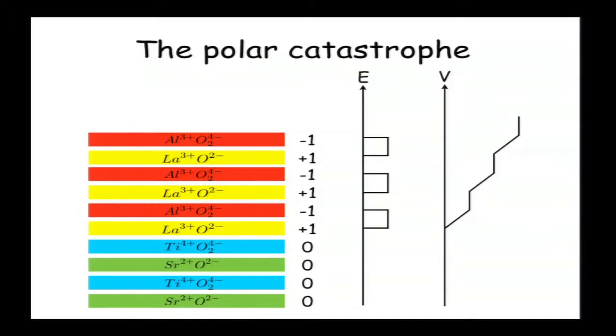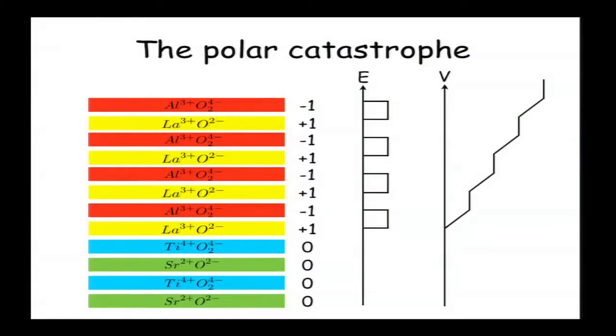Now, if we stop here, the system will remain as is, and we are not going to see anything interesting in the system. Instead of two boring insulators, we got one boring insulator, nothing more. But if we just add another layer, this voltage difference between the interface and the upper surface of the system is too high, and the system just becomes unstable. It cannot absorb this large difference in the voltage.